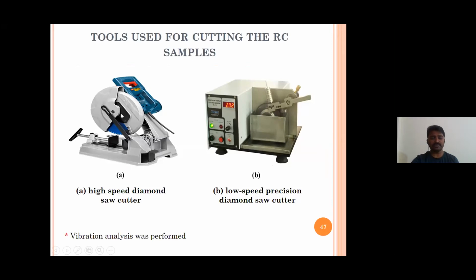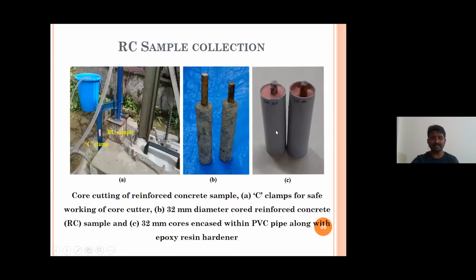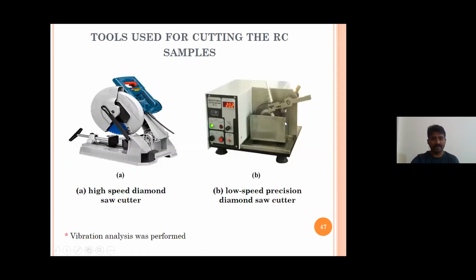In most of the journals or papers, people have used high-speed cutters, but in our case, when I use high-speed cutter, there is some disturbance to the engineering properties of steel concrete interface. As I'm cutting this sample, obviously there will be some amount of distortion. Because of that, the porous zone thickness was increasing. To avoid that, we have used even a slow speed precision diamond saw cutter.